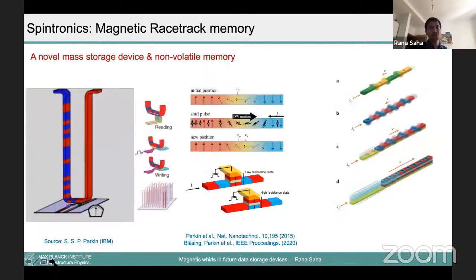But now there is another data storage technology which was proposed by IBM, by Stuart Parkin, where you can have a nanowire, a three-dimensional nanowire. In this nanowire, you can have magnetic domain walls. What is a magnetic domain wall? If you have a spin up and a spin down, the transition region in between these two is the domain wall. So what you can do is pass a pulse current and move this domain wall from left to right or right to left. And here, you can read at the bottom with a reading device or a writing device, something like that. As I mentioned in the previous case, the TMR, tunneling magnetoresistance, magnetic tunnel junction, can be used as a reading device.